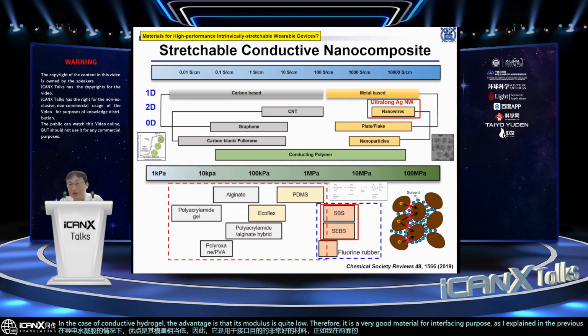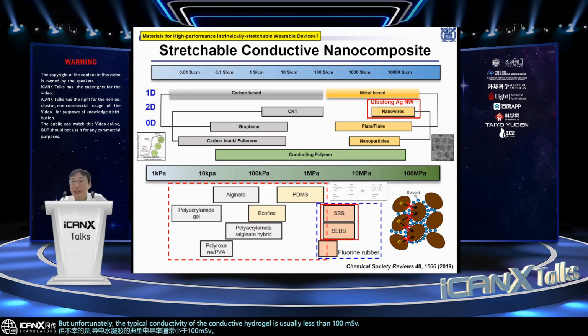But unfortunately, the typical conductivity of the conductive hydrogel is usually less than 100 milliSiemens per centimeter. Why? To increase the conductivity, we can add conducting filler like a conducting polymer or metal nanomaterial. But the problem is that hydrogels contain water molecules, and water molecules are polar. Therefore, they can trap electrons transported following the conducting filler. So due to this electron trapping, the signal transport can be significantly hindered, and that's the reason why the typical conductivity of a conductive hydrogel is less than 100 milliSiemens per centimeter.